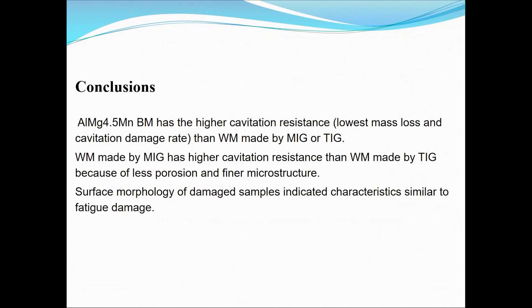To conclude: this alloy's base metal has, of course, the highest cavitation resistance, and then, as already said, MIG, with TIG being the worst. We should work on better technology for the TIG process to achieve better microstructure and less porosity. Probably 100% argon is not the best shielding gas choice in this case. Thank you.